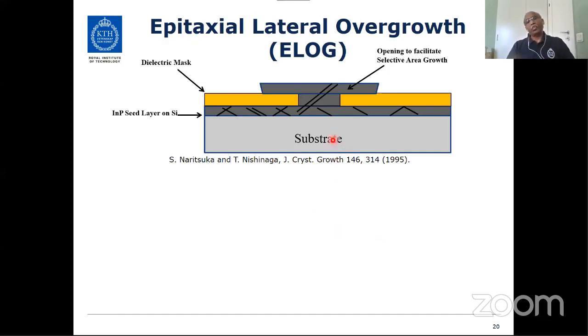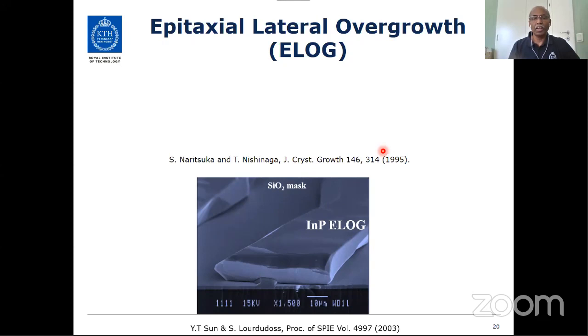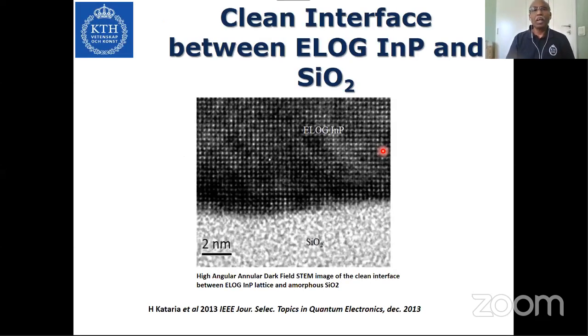And the good thing about this is, in the opening, you will propagate these defects, but they will not propagate above the mask. So this means the layer which you are growing away from the opening will be of good quality, and you'll be able to make use of it for making devices. And this was the very first indium phosphide ELOG layer we have grown on silicon. This is the TEM picture of the indium phosphide grown on silicon dioxide, I mean on the dielectric mask. Actually, the layer really adheres to the silicon dioxide surface. So it is a very, very clean material.